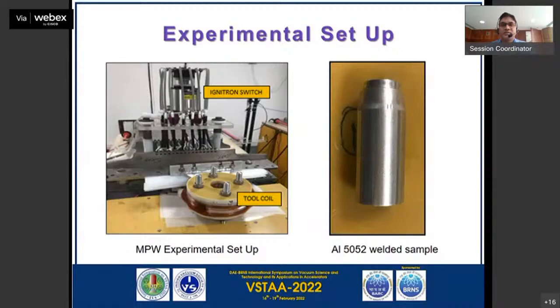Here we can see the experimental setup. On the left side, we have a capacitor bank upon which a switch is mounted, and the tool coil can be seen. This tool coil is used to generate that Lorentz force. When we have the aluminium tube and the target material inside it, and the current is discharged, this tube will be accelerated towards the target plug and will get welded.